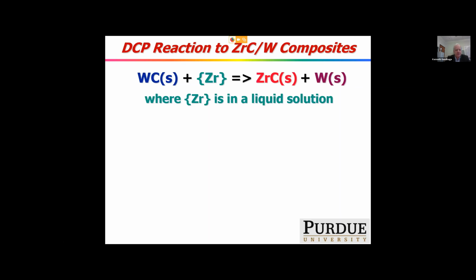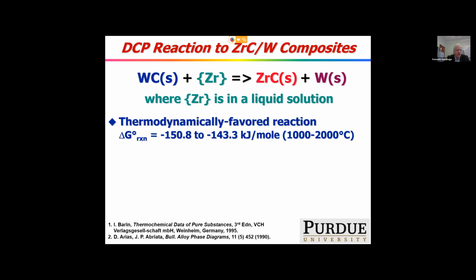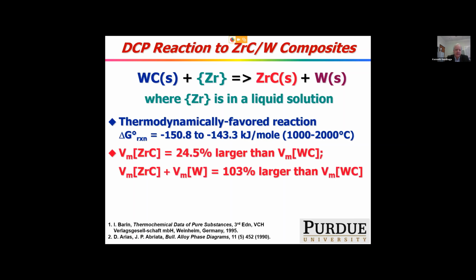Well, we start with porous tungsten carbide that we can form in a variety of ways using low-cost techniques that I'll show you shortly. We take that porous tungsten carbide preformed shape and we expose it to a zirconium-containing liquid. The zirconium in the liquid goes after carbon to form ZrC and tungsten. It's a displacement reaction. The carbon is displaced from tungsten carbide to ZrC, liberating tungsten in the process. This is a quite thermodynamically favored reaction over a wide range of temperatures. ZrC is a much more stable carbide than is tungsten carbide.